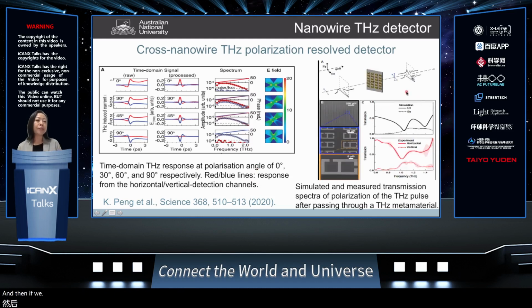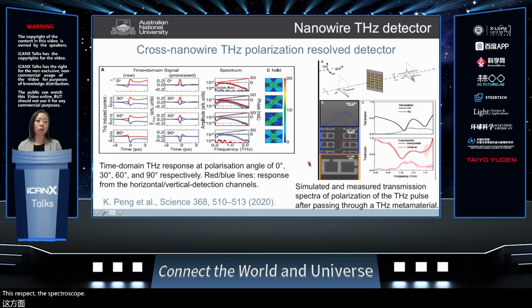And then if we use our nanowire to detect the transmission signal from polarization sensitive material structures, you can see that our experimental results are very consistent with the simulation results, showing that these tiny nanowires are very useful as terahertz polarization detectors, especially with the nano size. They will be very good for the near fields of terahertz spectroscopy or imaging systems.